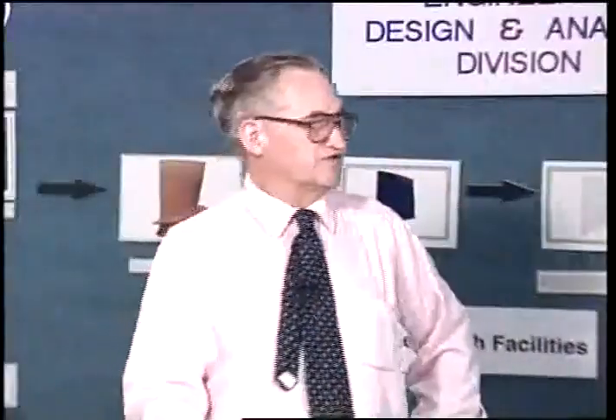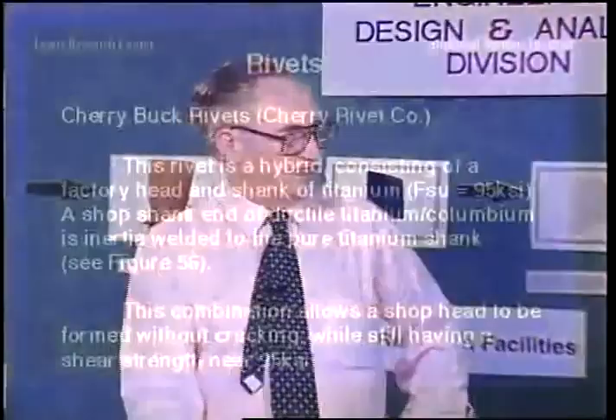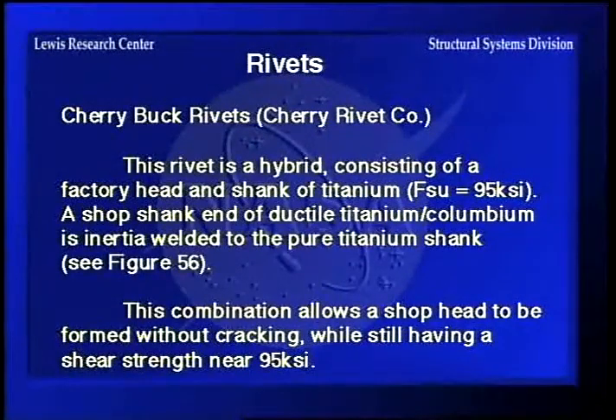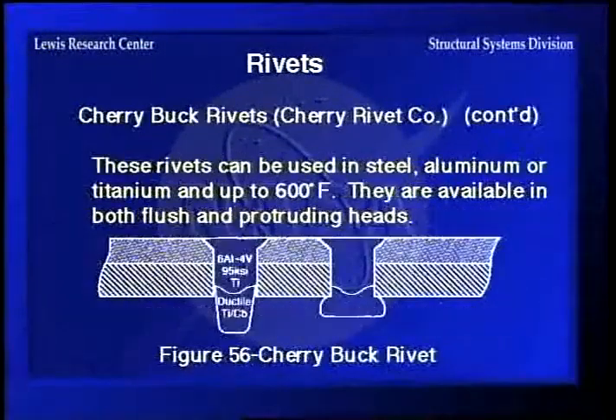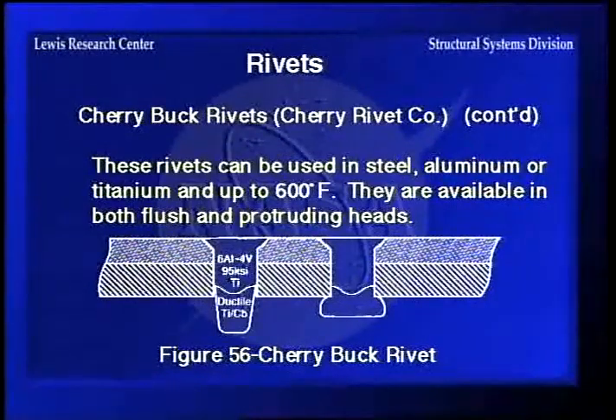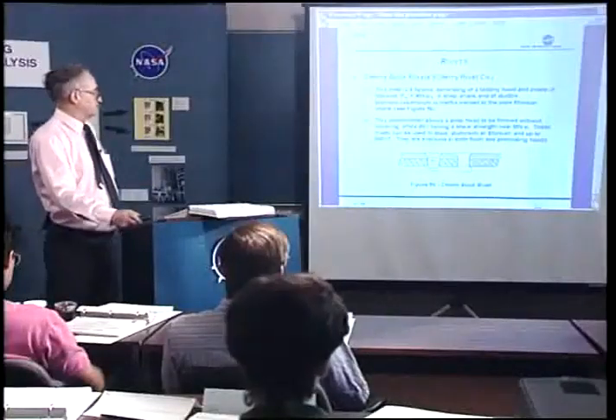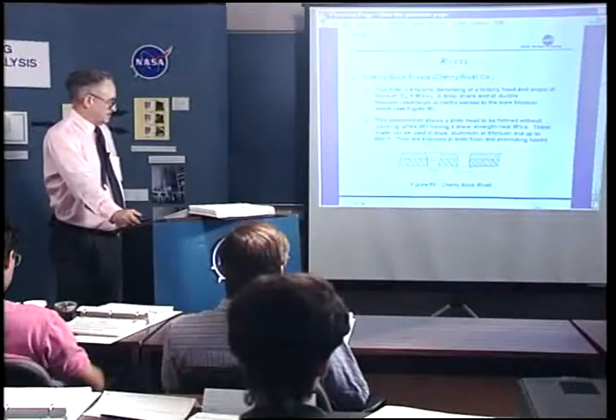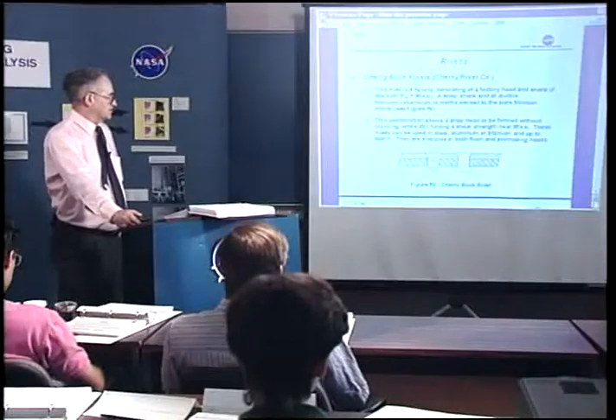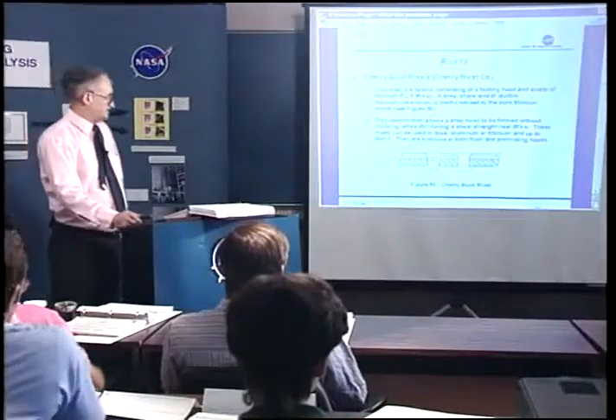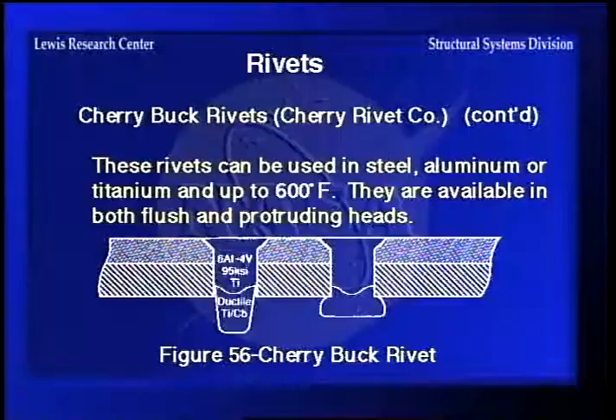Now here's the Cherry Buck rivet. That's the one I was thinking of. It actually has a friction welded piece of soft titanium on it, so that when you form it, most of the harder stuff is in the hole, so you only have a little bit of the softer material in the hole, so you get a higher overall strength, because this one has a shear strength up to almost 95 KSI, which is excellent. And they can be used up to 600 degrees, and they're available in both flush and protruding heads.